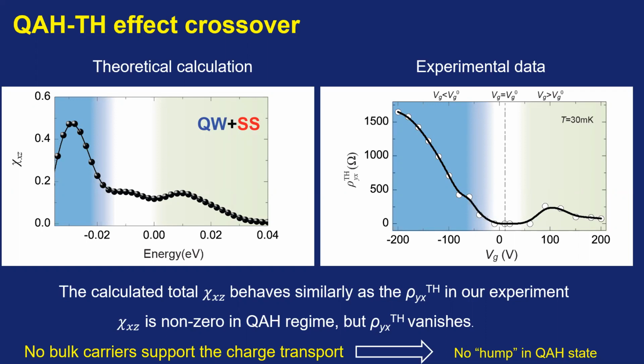The reason is that in the quantum anomalous Hall regime, the bulk is insulating. There is no carrier to support the charge transport in the sample, so there is no topological Hall effect observed in this kind of quantum anomalous Hall state. It's also reasonable.